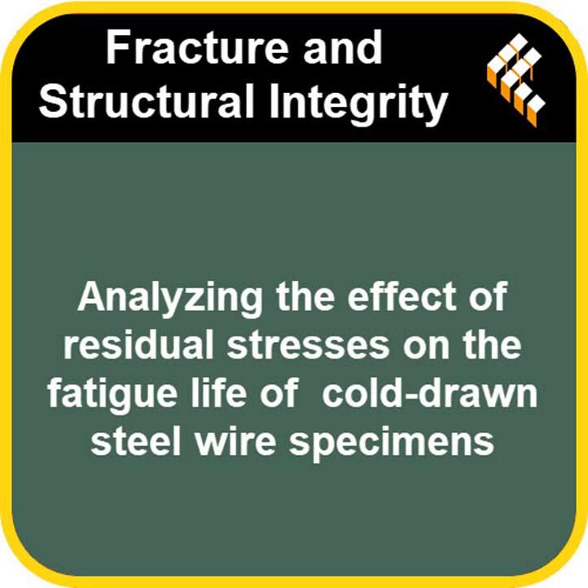Fascinating. So that's phase one, deliberately introducing a specific residual stress pattern. What's phase two? Phase two is the fatigue test. They take that same specimen, the one with the new residual stress, and importantly, they flip it upside down compared to phase one. Why flip it? Well, think about bending. Phase one likely created tensile residual stress on one side and compressive on the other. Flipping it changes how those stresses interact with the next load.